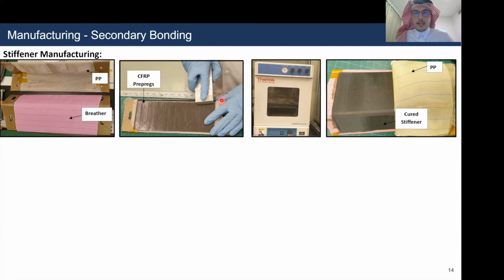Once the 8 layers were stacked, the mold was closed and locked with some bars and inserted into the oven. In the oven, they were heated for 2 hours at 180 degrees under vacuum of 25 inches of mercury. After the T-joints have been cured, they were removed. The peel-ply was removed, and this was considered to be the peel-ply treated T-joints.